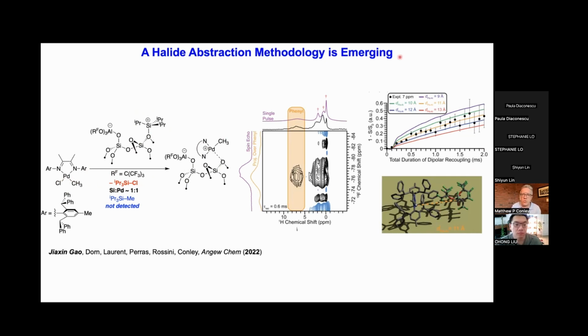What I'm showing here is a really complex NMR experiment that was done in collaboration with Fred Perras at Ames National Lab. This is a proton fluorine experiment where he's able to take these parameters and use this dipolar dephasing curve, which is similar to that aluminum experiment I just mentioned. And he's able to fit this to a single parameter, which is the palladium aluminum distance, which turns out to fit very well to 11 angstroms, which is precisely what you expect for a bulky weakly coordinating anion interacting with a bulky weakly coordinating cation.